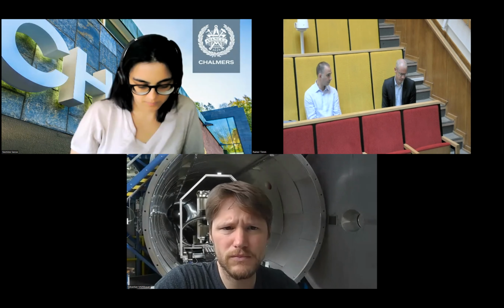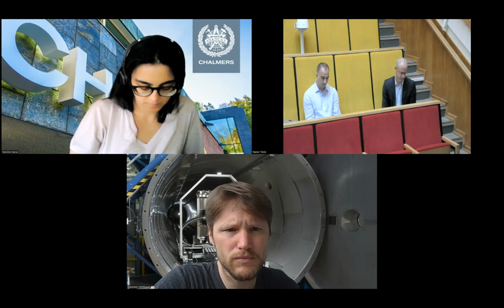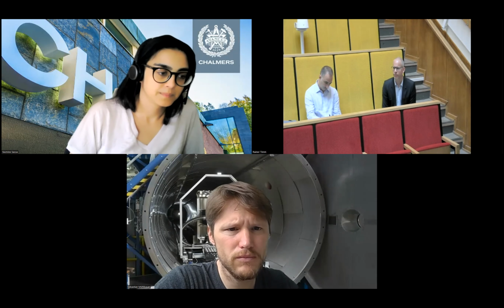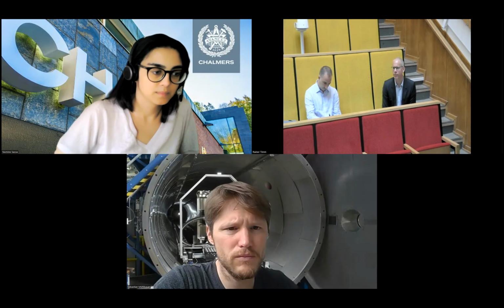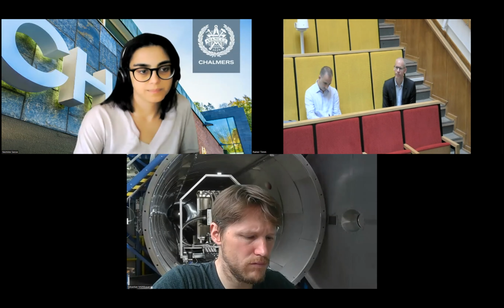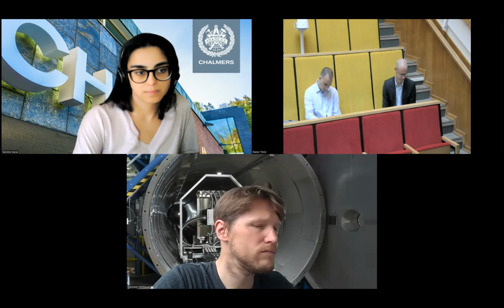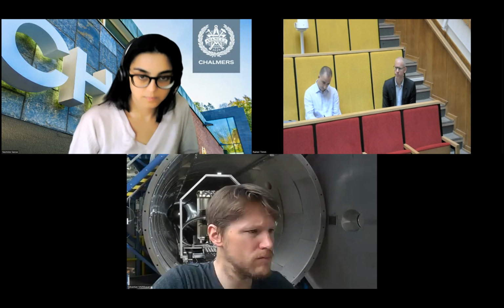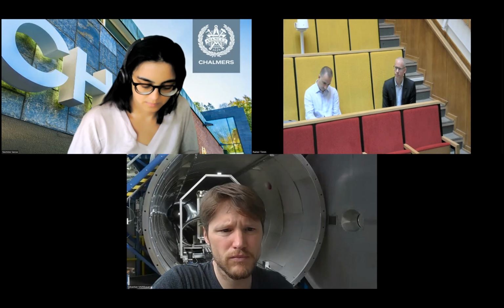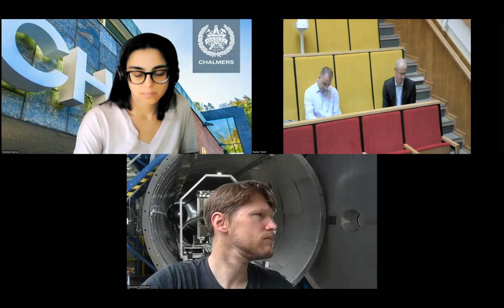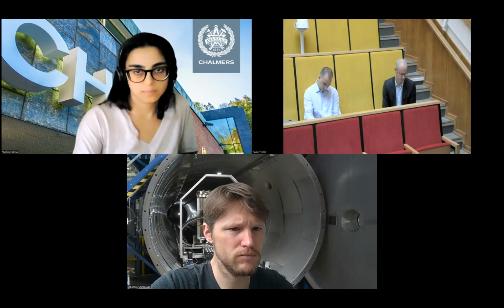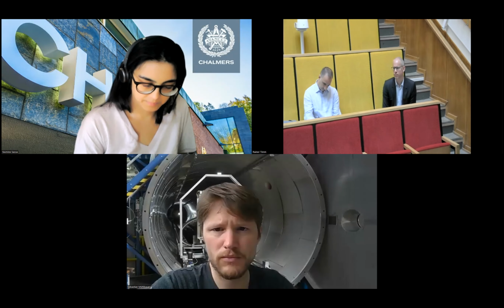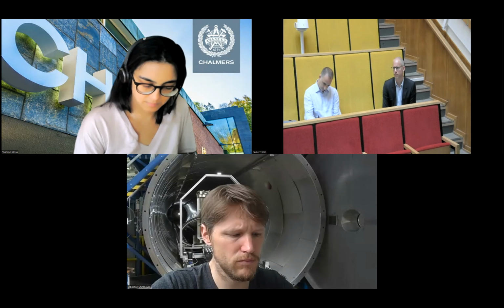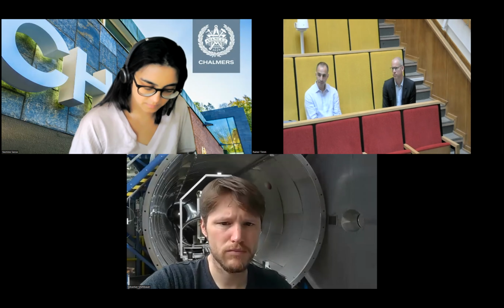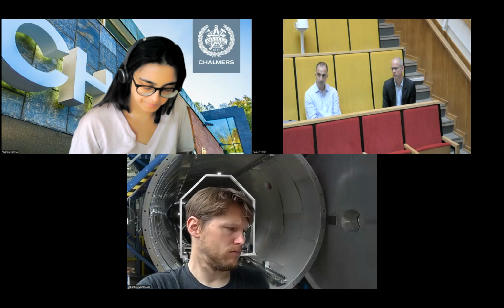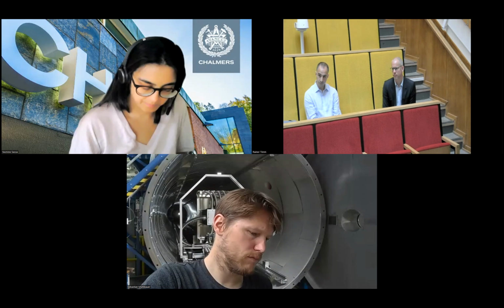Yeah, so you're right that this bismuth palladium might be a topological superconductor. Do you know why people have that suspicion? Where does that come from? From the lead tantalum selenium 2 and the gold lead, they observe these Dirac points that are characteristic of these kinds of materials. But in the case of this beta bismuth palladium, you have two different gaps arising under certain conditions, one related to the surface of the superconductor and the other related to the bulk. And that may be related to topological characteristics of the superconductor. That's why it is considered a good candidate.